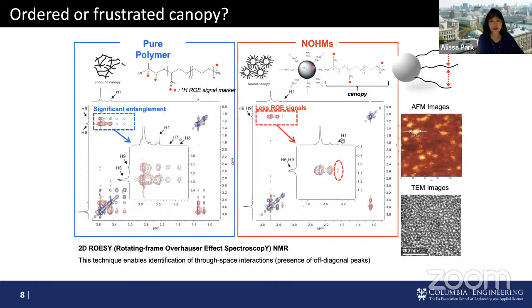What it means is that the tethered polymer here in NOHMs, compared to untethered polymer, was more stretched out and far away from each other, in a sense creating a lot of free volume in between. So we were showing that by tethering polymers, we can change the structure and conformation of the polymer itself and also the distance between polymers, creating very interesting cavities for free volume.